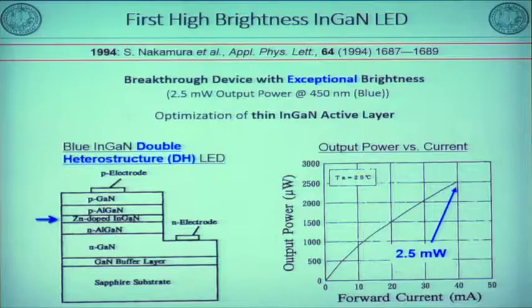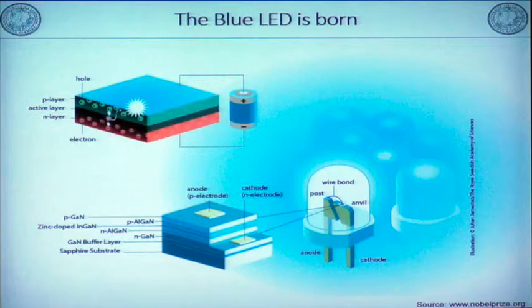So in 92 we developed double heterostructure LEDs, and the active layer is indium gallium nitride, sandwiched by N-type gallium nitride and P-type gallium nitride. So we can make very high efficiency, very high power blue LEDs in 93. At the same time we started the commercialization. Output power is 1.5 milliwatt at 20 milliamp. At 2 milliwatt is fine. But the PN homojunction is on the order of microwatts.